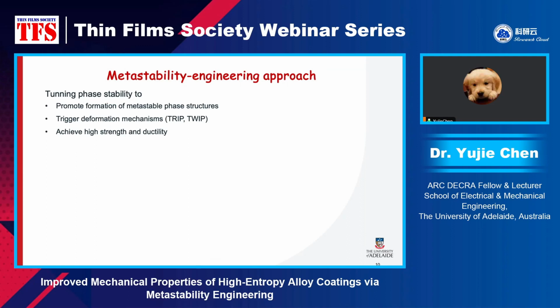So the idea here, basically, is that it tunes phase stability to promote formation of desired phase structure, such as the dual phase structure, and to trigger the deformation mechanism. Normally, it's TRIP and TWIP. You may have heard of TRIP steel and TWIP steel. TRIP is transformation-induced plasticity, and TWIP is twinning-induced plasticity. So here, we try to trigger the phase transformation and the deformation twinning. As a result, we will achieve high strength and ductility.